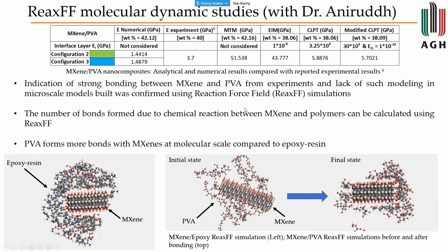So we had to perform a molecular simulation called the reactive force field simulation, where we would have molecular level simulations of MXene with epoxy resin chains as well as polyvinyl alcohol chains. The number of chemical bonds that are formed with epoxy resin and MXene is quite less compared to polyvinyl alcohol. This leads to the understanding that there are more bonds formed on the surface, resulting in a stronger interface region. The interface region between MXene and polymer would play a major role in further development of these models.